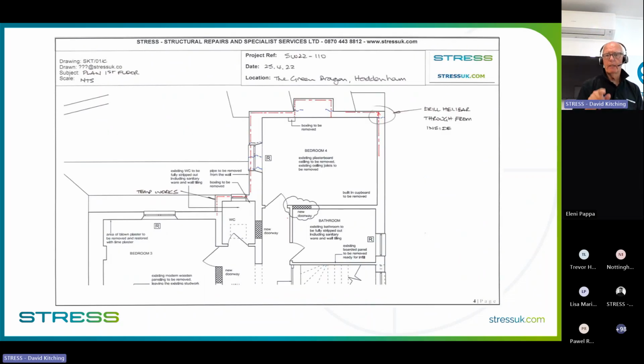Now, one of the reasons I want to show you this is in plan, you're now looking down, top right-hand corner there, on that gable wall onto the flank wall, and there's that discontinuity. What we see a lot of in design, and also when we get to some sites, is that the repair that's been put forward is to run the helibar around the inside of the corners. That doesn't really work, because if that gable wall wanted to move north, up the page, and you had helibar running around the inside, all it would do is pull the helibar out of the wall sideways. So you really want to use the stainless steel bar in tension at all times. So you actually drill through and return the bar on the outside. And you can do this almost anywhere. It's a little bit more work, but you get a much more effective repair.